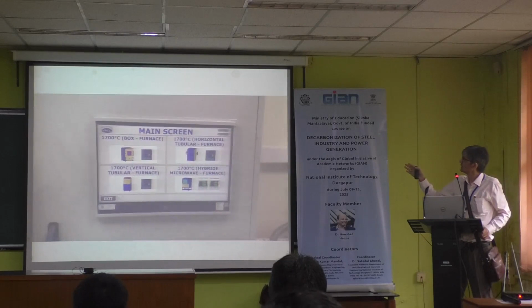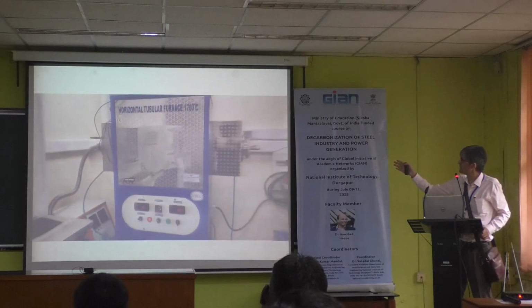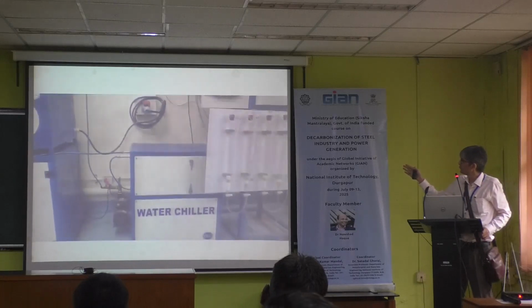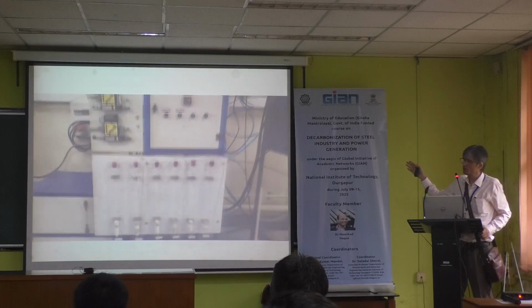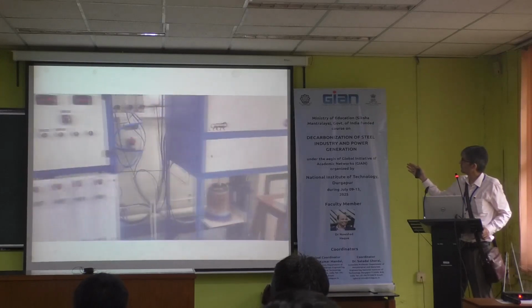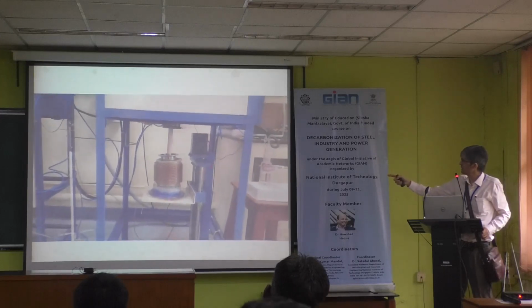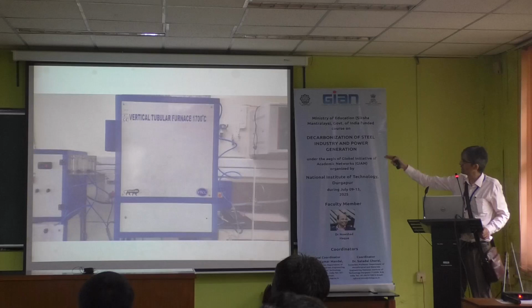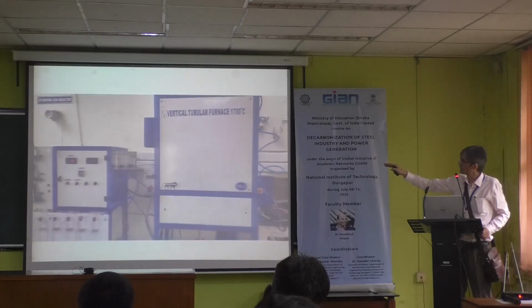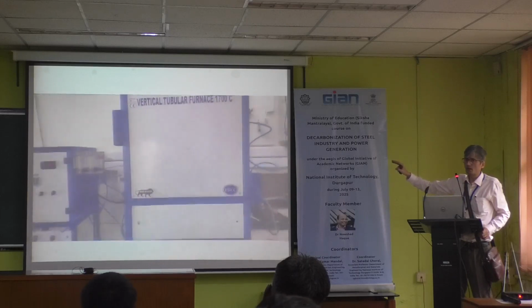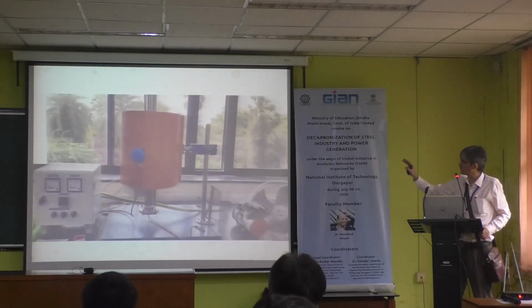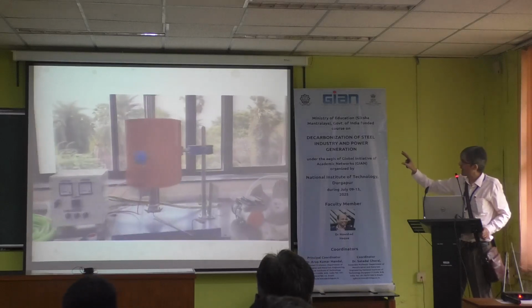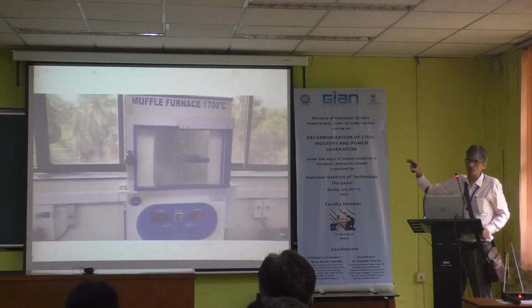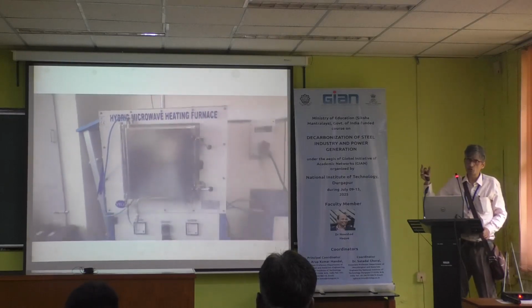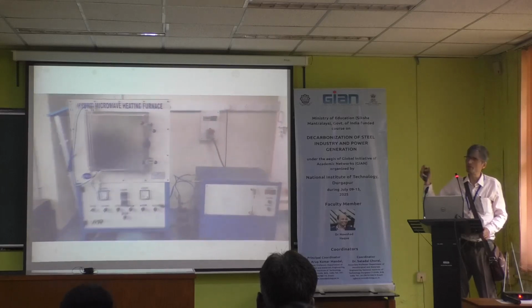This is a Davis tube, a high intensity magnetic separator. Then there are a number of furnaces: a horizontal tubular furnace which can go to 600 degrees centigrade, and a vertical tubular furnace where these hydrogen experiments are going on. From here, the weight of the sample can be measured from the bottom, from the rod, and the sample goes into the center, and we can control the atmosphere in terms of carbon monoxide and hydrogen. For carbon monoxide, we don't use a cylinder. We have not done any experiment with carbon monoxide directly, but we have another tubular furnace where we heat coke at high temperature and pass carbon dioxide through it. In this way we generate carbon monoxide.